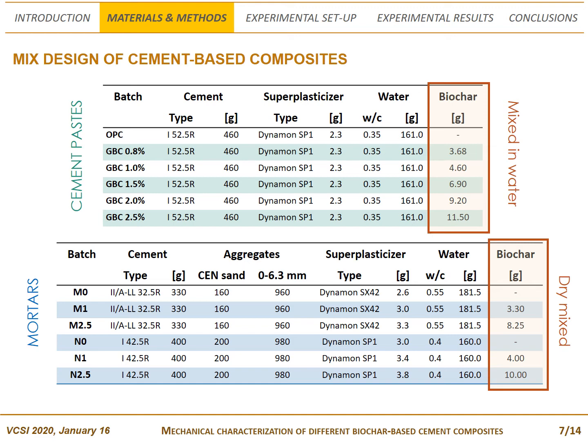As regards mortars, two different admixtures were prepared. The admixtures denoted as type M simulated a ready-mixed concrete, while type N referred to a mix for precast concrete. They differed mainly for the adopted type of cement and for the water to cement ratio. As biochar tends to absorb water, the superplasticizer percentage was increased with increasing biochar addition, in order to get about the same flowability as the control batch. It is worth noticing that in case of mortars, biochar was added dry to the admixture together with cement.